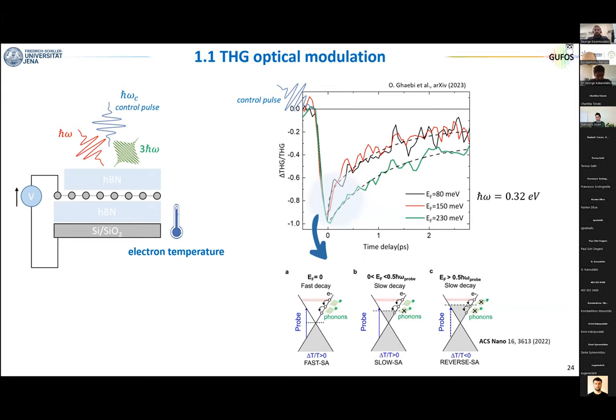This is a sort of Pauli blocking or a phase space filling or a phase space quenching. So in this case, you cannot emit an optical photon anymore. And then of course, this dynamic must be fully suppressed. And this is indeed exactly what we observe also in this third harmonic experiment.